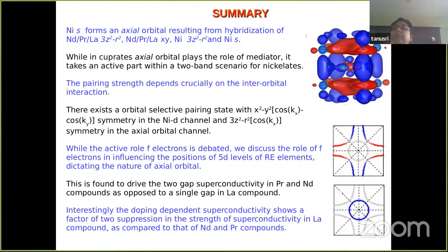While the active role of the f electrons is debated, because in our calculation we have put the f electrons in the core, what we are actually talking about is the role of the f electron in influencing the position of the empty 5d levels of the rare earth, dictating the nature of the axial orbital. It is found to drive two-gap superconductivity for the praseodymium and neodymium compounds as opposed to a single gap in the lanthanum compound, because, as already mentioned, of the diminishing of this electron pocket, in the case of the lanthanum compound only one channel becomes operating.